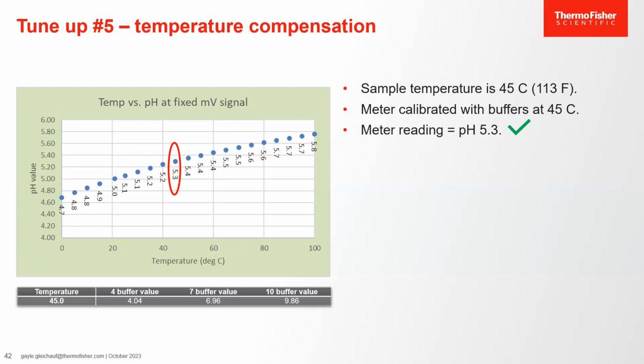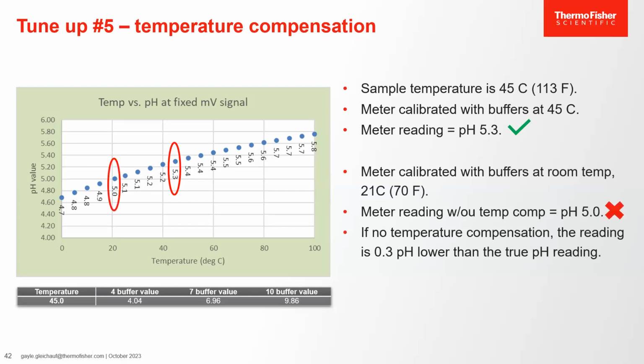However, if I calibrate my meter at room temperature, for example, 21 degrees C, while my sample's at 45 degrees C, I won't get accurate results without temperature compensation. In this case, my meter would read pH 5.0. This would give me an incorrect pH reading that's too low by 0.3 pH units. If I do have an ATC, temperature compensation will be automatic. The sample temperature will be measured and the calibration slope will be adjusted for that temperature.